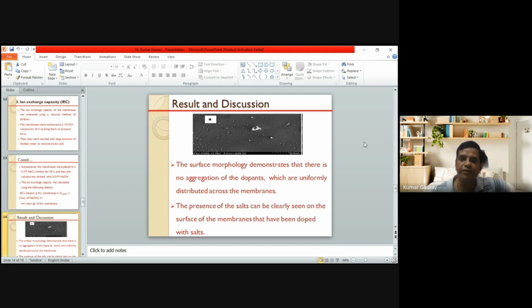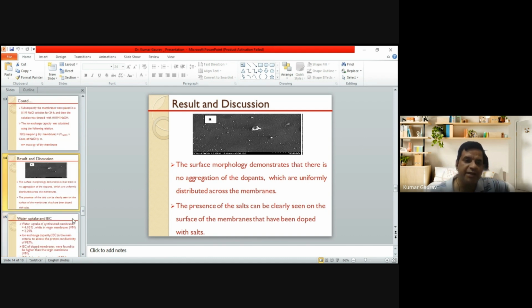So now we come to the discussion part. First of all, we look at the surface morphology. The surface morphology shows no aggregation of the dopants like potassium thiocyanate and citric acid. They are uniformly distributed, and the presence of the salt can be clearly seen, so the surface of the membrane is doped with the salt. So this is the SEM analysis.